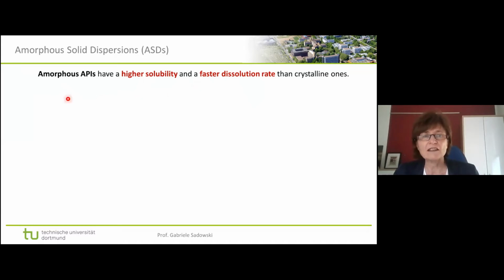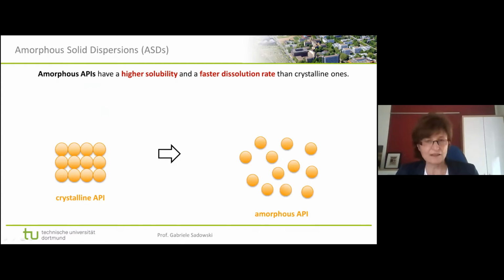So the idea, which pharmacists are already investigating, is to formulate an API in an amorphous state. This is the crystalline one, and the amorphous state has the advantage that you do not have a crystal lattice anymore, which needs to be broken during the dissolution process. So dissolution of an amorphous API is much faster, and solubility is also higher than that of the crystalline one.